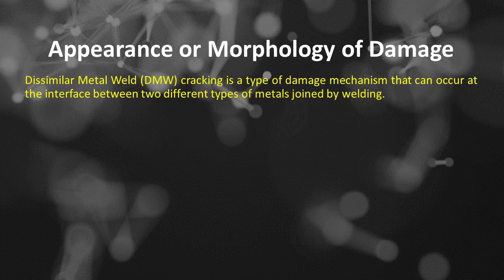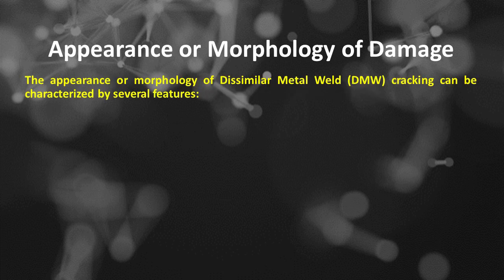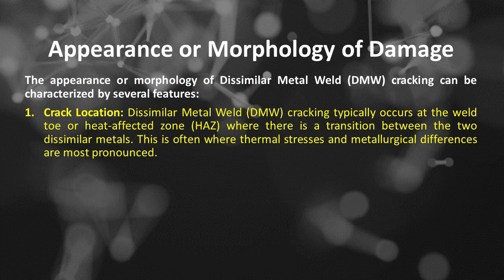Dissimilar metal weld, DMW, cracking is a type of damage mechanism that can occur at the interface between two different types of metals joined by welding. The appearance or morphology of DMW cracking can be characterized by several features. Number 1 is crack location. DMW cracking typically occurs at the weld toe or heat-affected zone, HAZ, where there is a transition between the two dissimilar metals. This is often where thermal stresses and metallurgical differences are most pronounced.